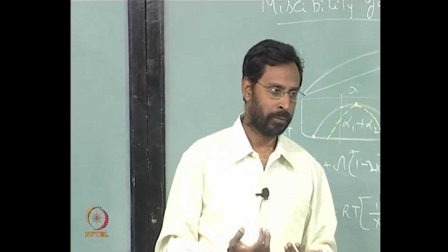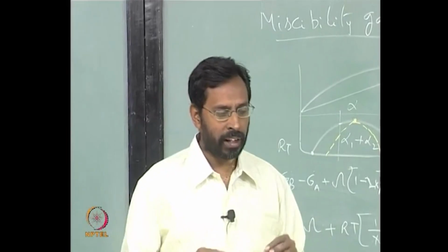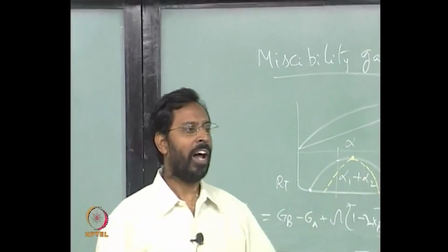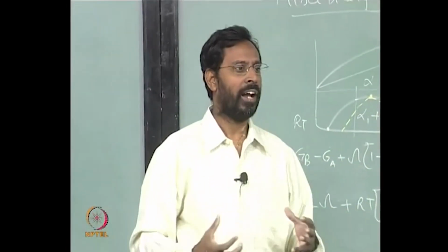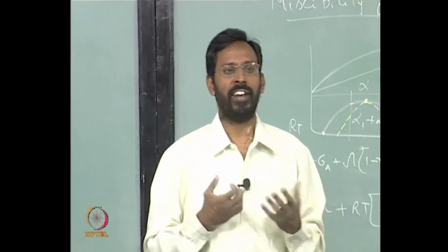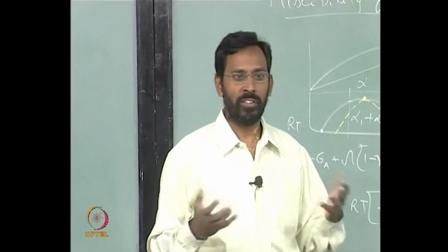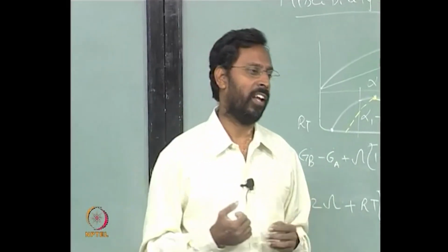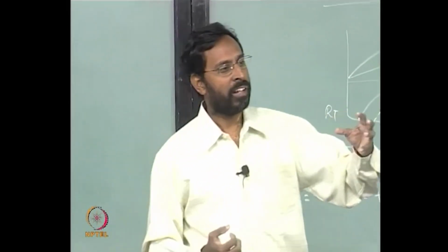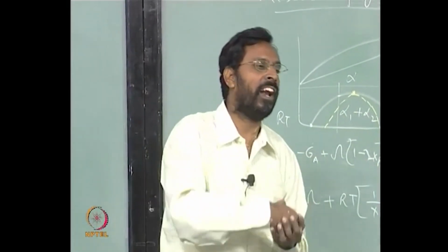But will that not lead to the intermetallic component? It need not, because the question is whether it would like to form a regular configuration or it would like to have a randomly sitting and then giving you a high dense random packing. We call it dense random packing. It is dense, but it is a random packing. So such kind of structures are all there. There are so many liquids. That is why we say bulk metallic glass is that where the viscosity is very high. Viscosity, why is it high? Because it has a dense random packing.